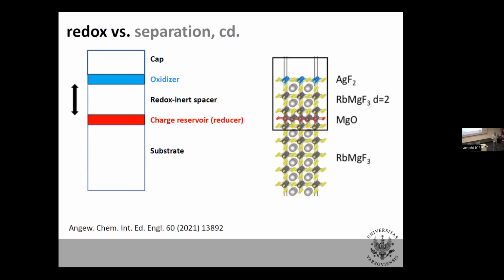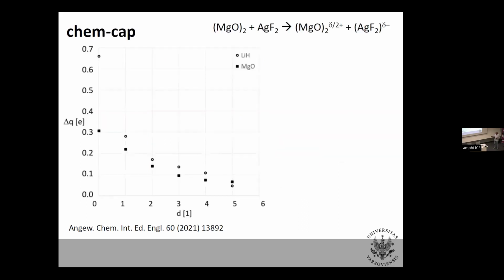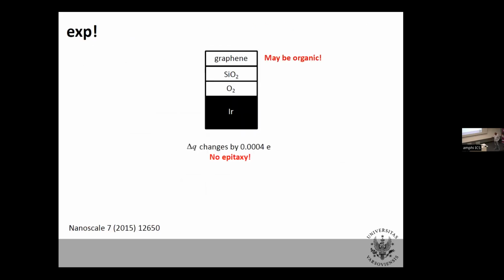So in their case, and as you know, this effect really decreases substantially with thickness. It must, because if you separate layers to infinity, the same thing as cesium and fluorine, nothing will happen. Electrostatics is not paying back. So they saw small effect of hole doping to graphene, but sufficient to be seen. Why so small? Because of a huge thickness of silica.